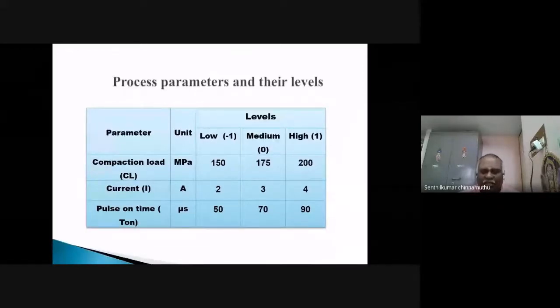Three parameters, three levels: compaction loads of 150, 175, 200. Three various compaction loads are used to compact the specimen to evaluate the coating characteristics. Similarly, we use three levels of current: 2 amps, 3 amps, and 4 amps, and pulse on time of 50 microsecond, 70 microsecond, and 90 microseconds. So, with three parameters and three levels, 20 experiments are conducted according to the central composite face-centered design. And the experiments were conducted.